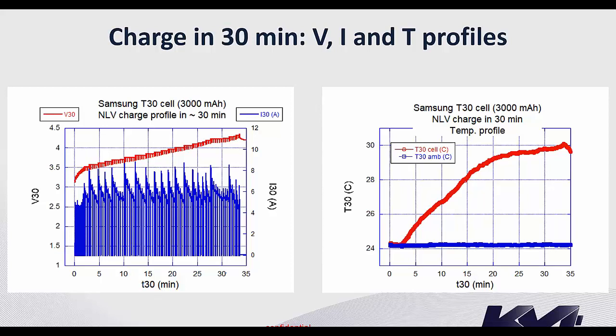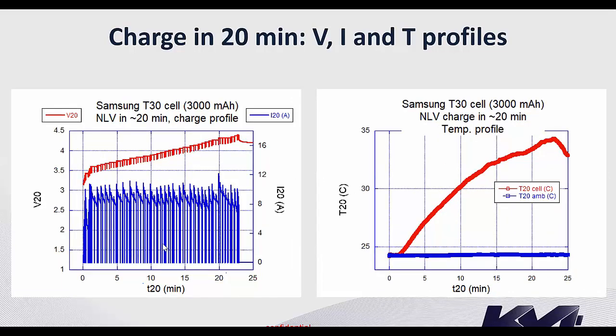So this is the profile of the same cell when we charge it in about 30 minutes. Okay, you can see that the voltage is almost the same as in the 1 hour. It has many plateaus, the voltage plateaus here, and the current profile here. And the voltage is higher than 4.2 volt. It goes to almost 4.3 volt. And the temperature when we charge the battery in 30 minutes is about 30 degrees C, which is still very, very cool. Okay. Now, if we go to 20 minutes, it's a little bit more than 20 minutes, 22 minutes. We can see that the voltage is a little bit higher. It goes to 4.335 volt, and the current is the same. You know, it's never constant, and the temperature is about 34 degrees at the end of charge.